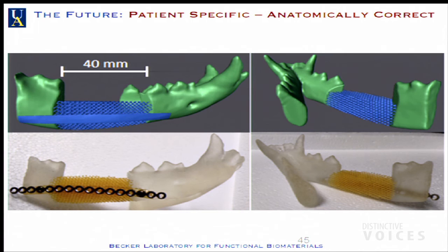And so here's the in silico design. We've got a plastic part here, but it's well defined enough that you can actually predict where you might want to tap the screws to use metal plates on a first pass, but then actually use plastic or fully degradable sections on the end. And I can tell you that in the dog models and in the artificial bite devices that we're using, even though this is only 12% solid, it's actually strong enough to create enough force that this could potentially chew.